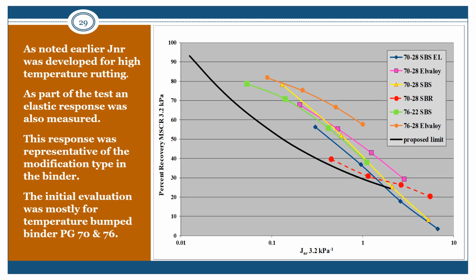However, in this case, we plotted it on a log scale for the Jnr value, and it's a little bit easier sometimes to see how these materials look different. A good example would be the 2 PG 76 grades. Here's a 76-22 made with SBS, and here is a 76-28 made with Elvaloy. Now, at 76 degrees on the testing properties, they're both basically what we call 76H grade. But they have very different recovery properties.